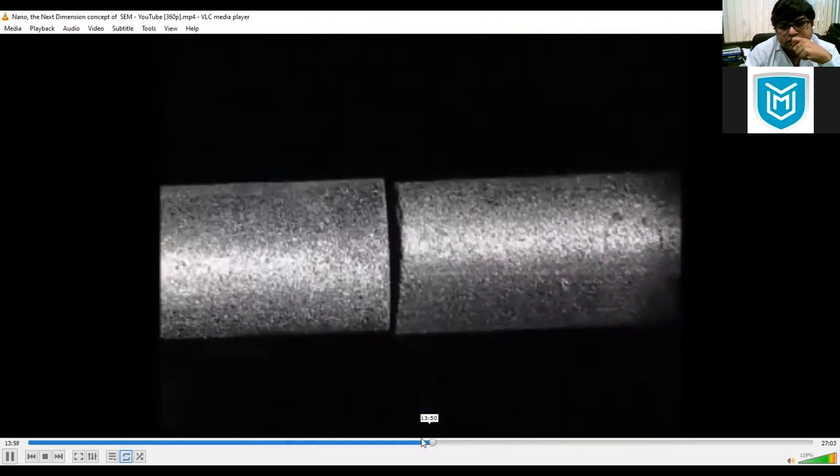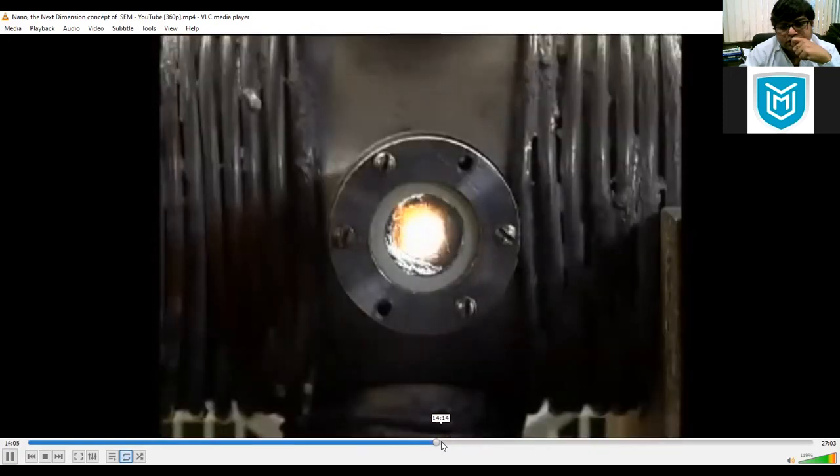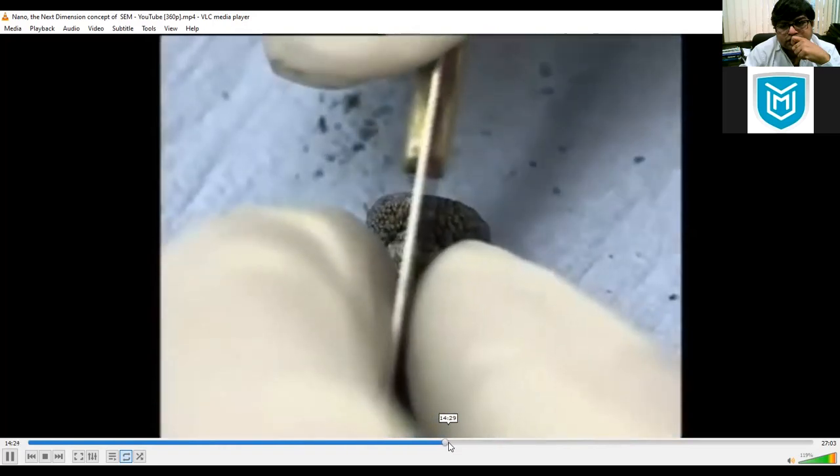To obtain nanotubes, take two pure carbon graphite electrodes connected to a DC generator in an atmosphere of helium, an inert gas that does not react with carbon. At 4,000 Celsius, the graphite fuses and matter torn from the electrode on the left is deposited on the right-hand one, forming nanotubes. After cooling, they can be collected from the freshly produced tip.